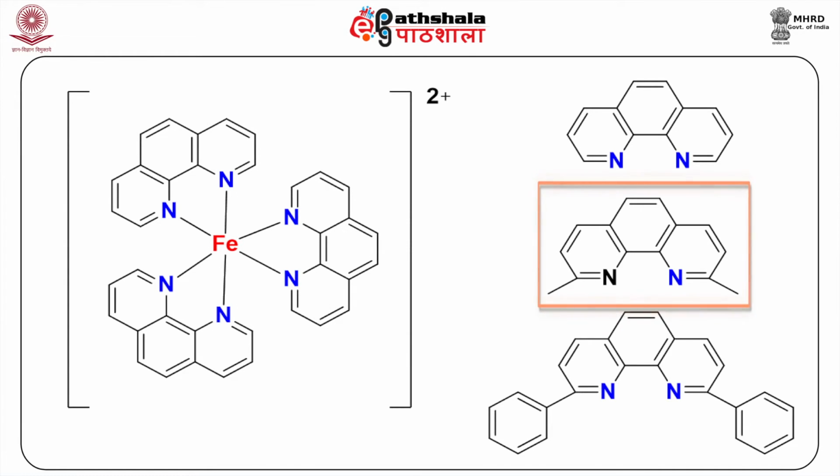steric hindrance is even stronger and weakens the ligand field strength further, yielding high spin behavior of the tris(2,9-CH3 twice) complex down to very low temperatures. It was found that a combination of steric hindrance due to bulkiness and an electronic influence of the substituent on the basicity of the coordinating N atom are responsible for the influence on the spin crossover behavior.